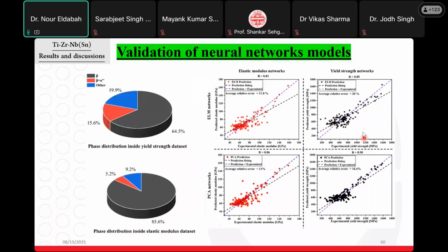Also, for the yield strength, the average relative error is high, around 20%. And as you know, as a metallurgist, the yield strength is affected by many factors, for example the grain size, the number of dislocations that exist in the alloy, and the affinity or the oxygen content inside your alloy. So it is difficult to build a very accurate machine learning system that can predict the yield strength of your alloy.